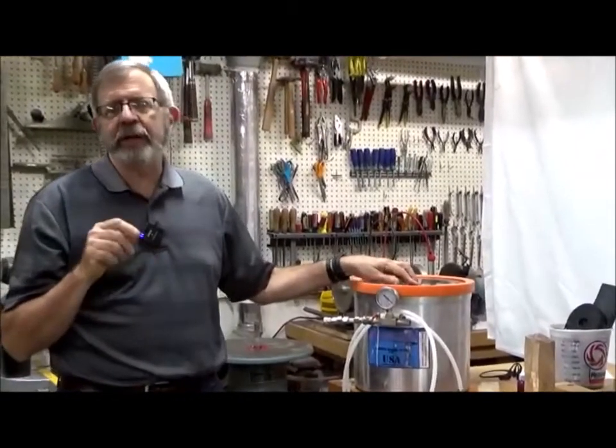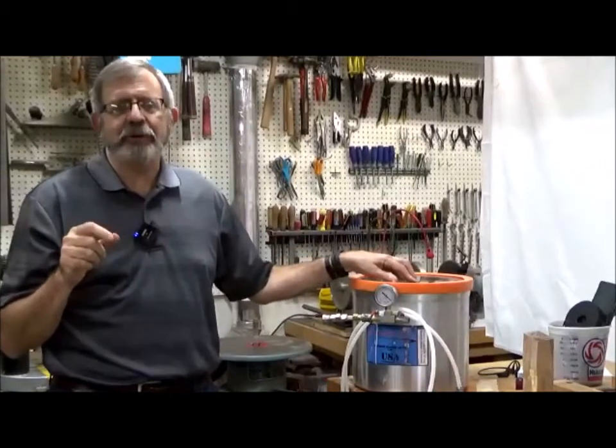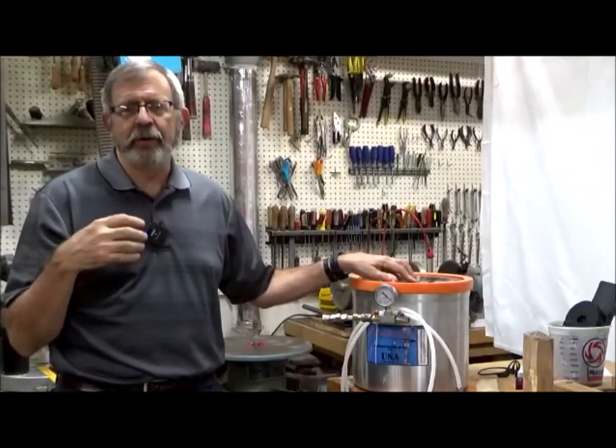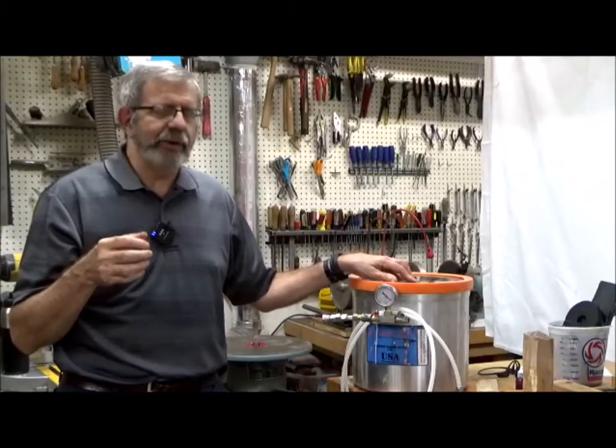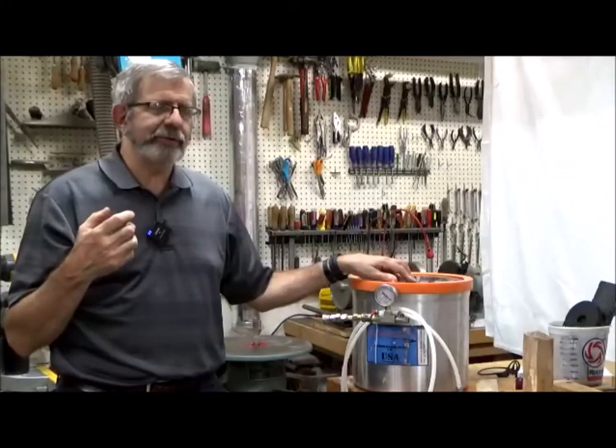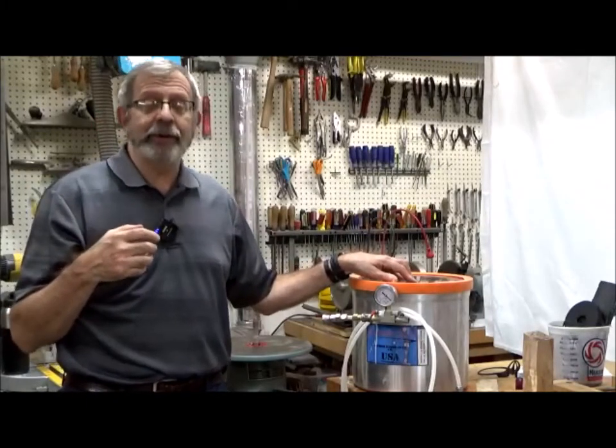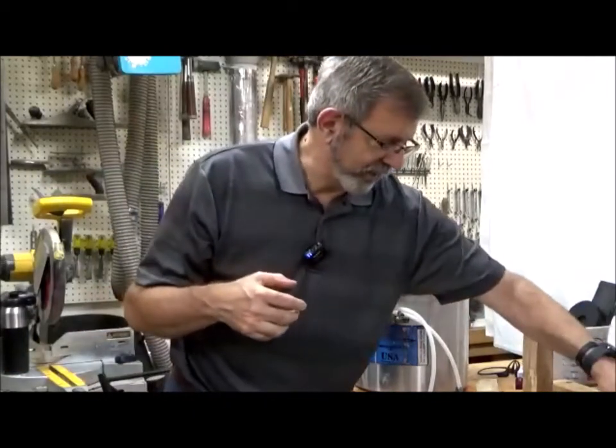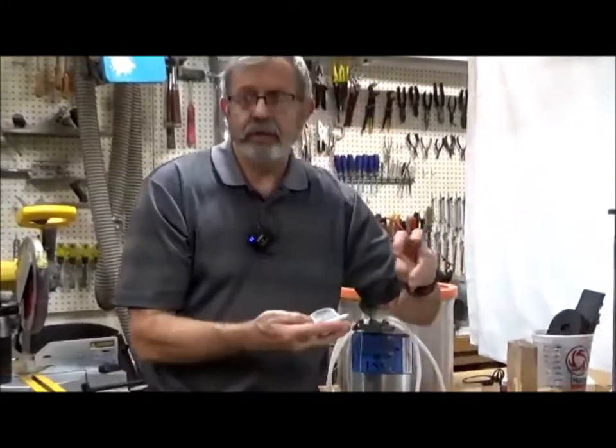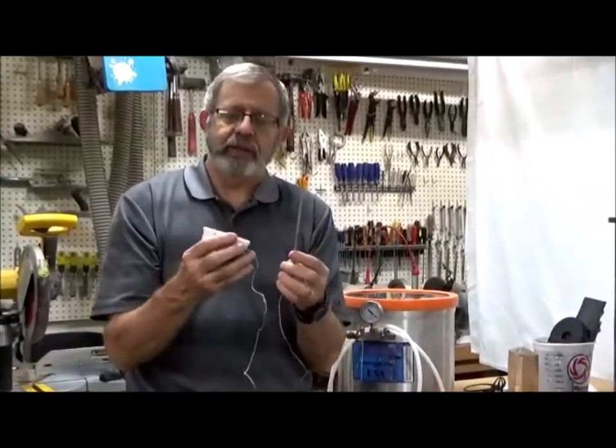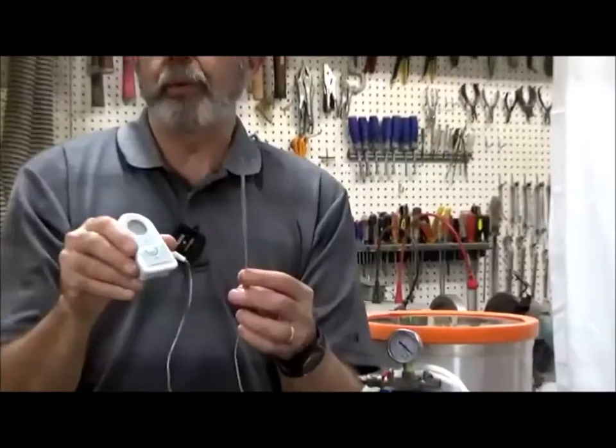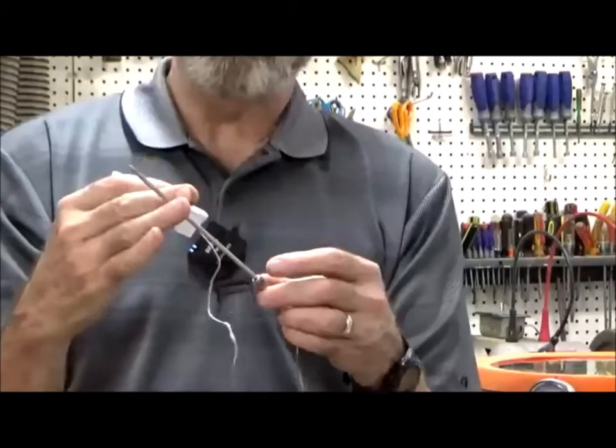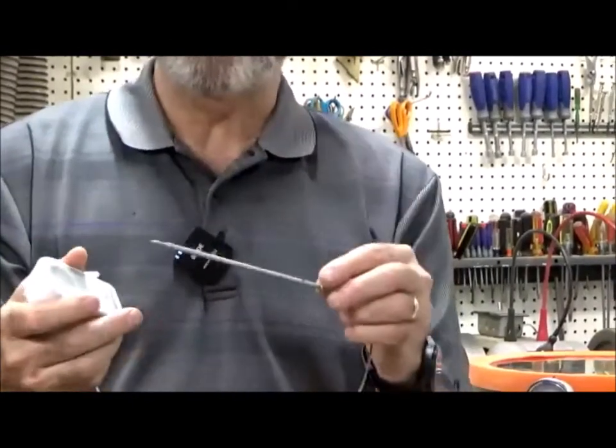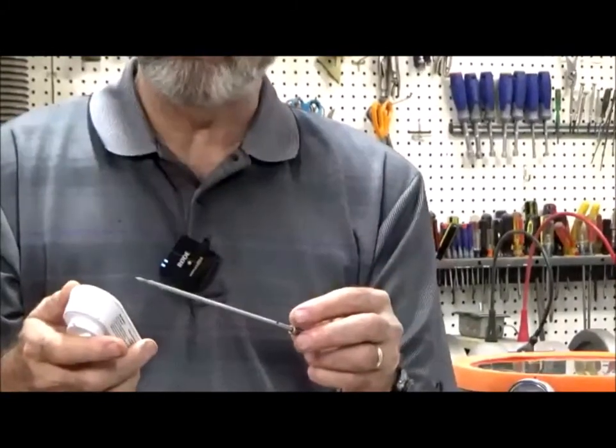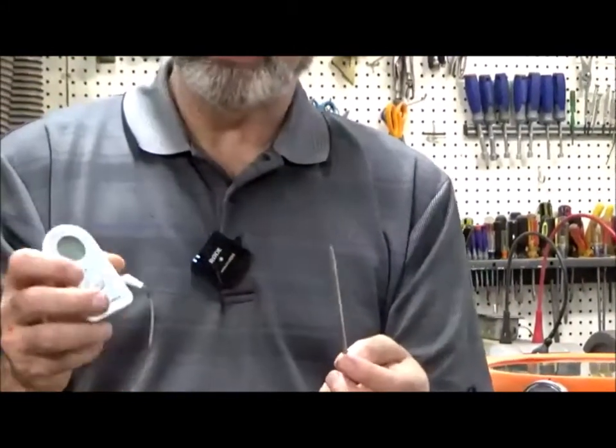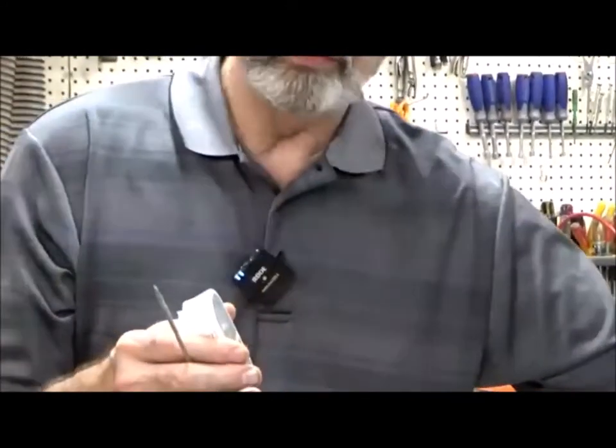At temperatures between 190 and 200 degrees. Absolutely. You have to get to that temperature, but you can't set it too high or it'll all evaporate out before it sets in your wood. So it's very important that you maintain temperature control. The temperature controls on most toaster ovens are not anywhere near accurate. So I found it very beneficial to have one of these little, this was a $35 temperature probe made by a company called ThermoPro. What's nice about this is I wrap the probe in foil and stick it on top of the wood samples that I have in there. And this has a digital readout, but it also has a remote display.